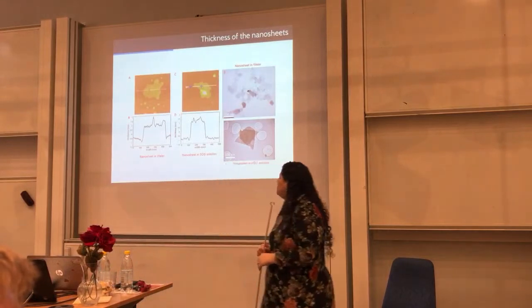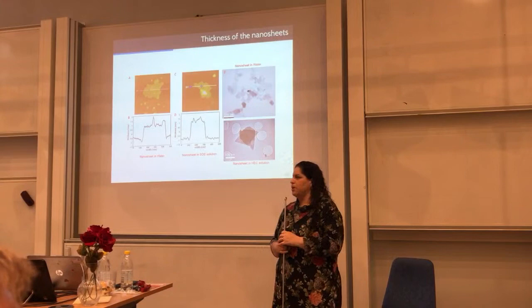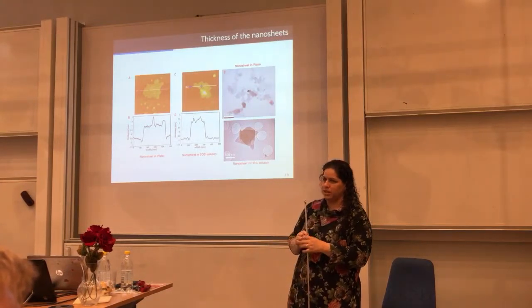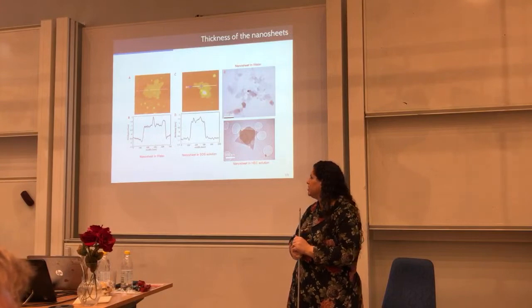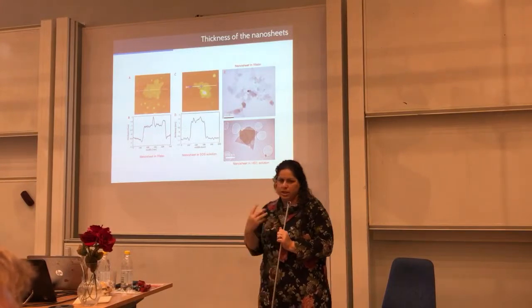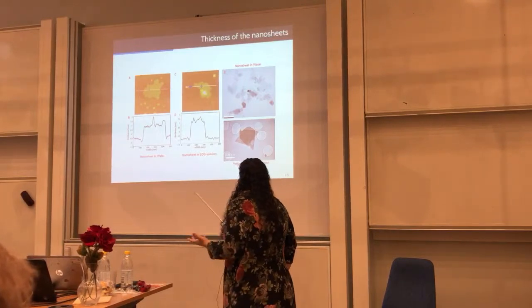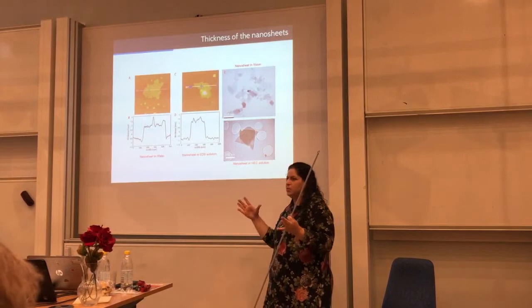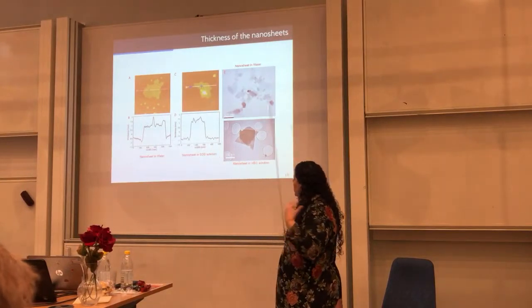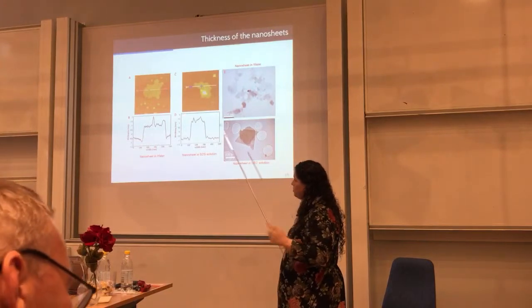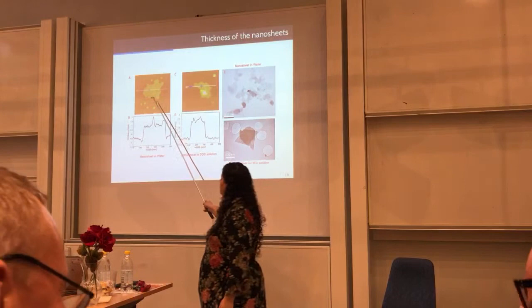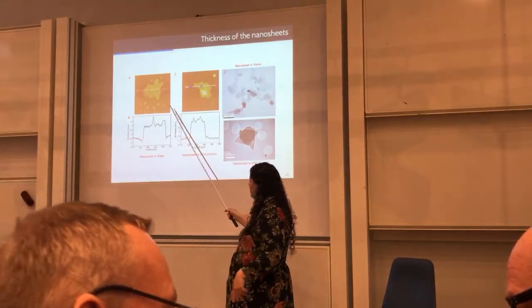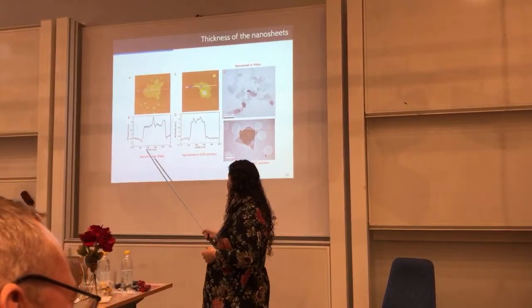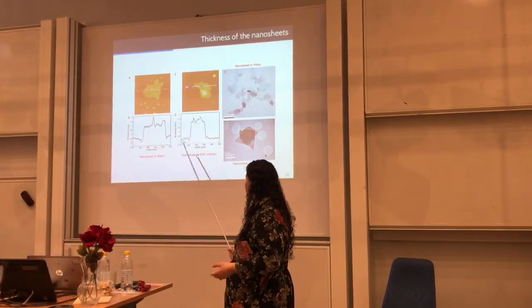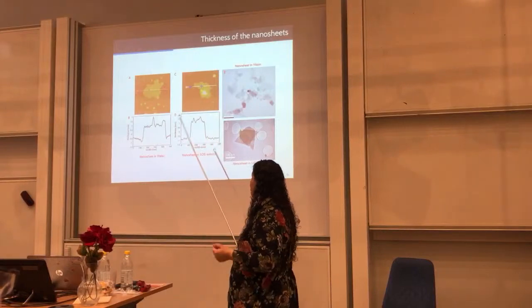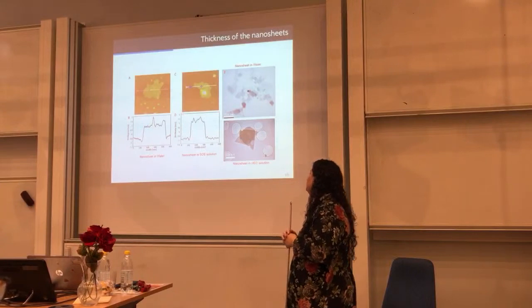Okay, so we did exfoliation in water. We have our dispersion that doesn't look so crystal clear, so we know that we did some individualization of the particles. Then we need to study how well this exfoliation happened. And how do we do that? We use techniques to measure the size of the particles and the thickness. Here in our university, we used to have an AFM. With AFM, you can measure the size of these platelets when they are deposited on a silicon wafer. And they were in the range of 300 to 400 nanometers. And it's the same in surfactant. They were all in the same range as is present in the literature.